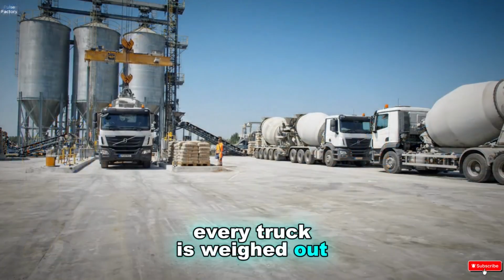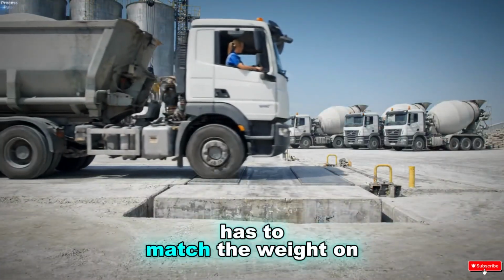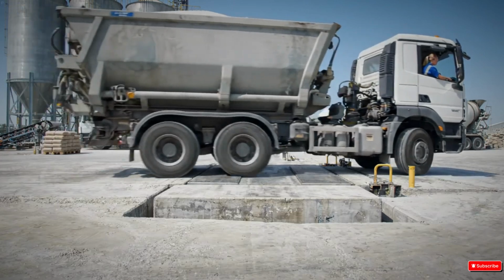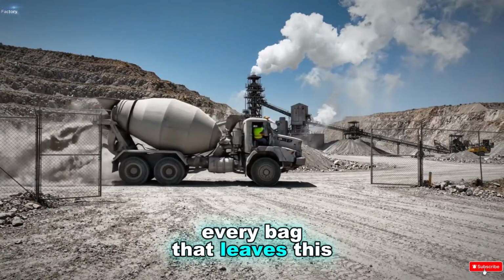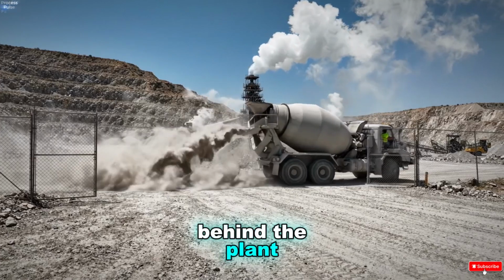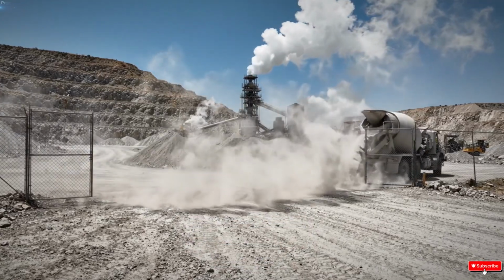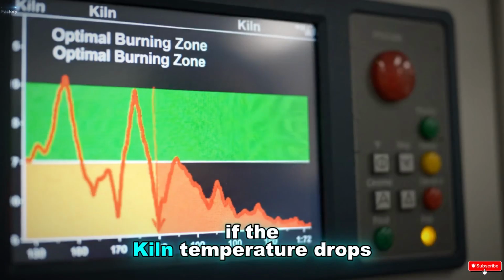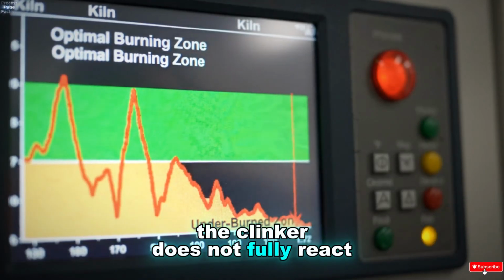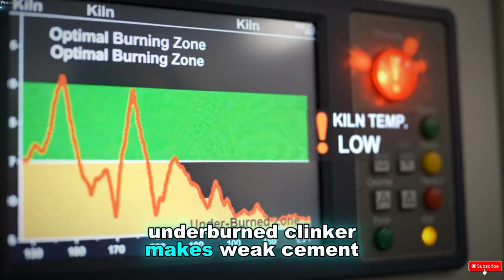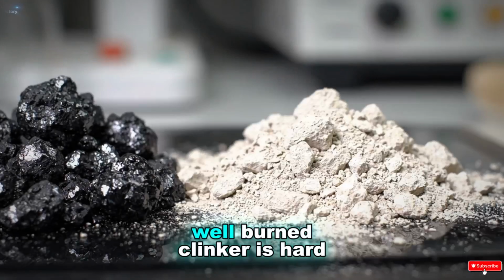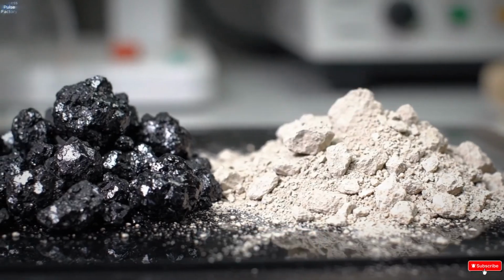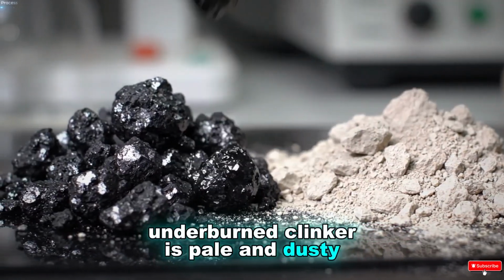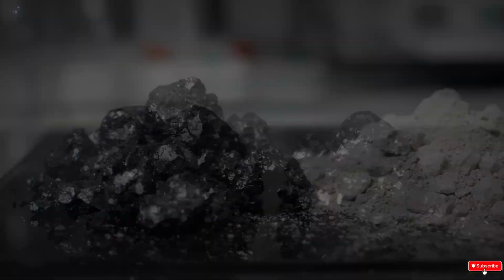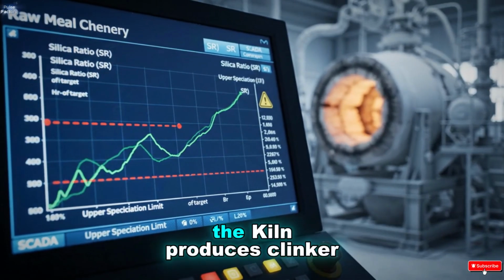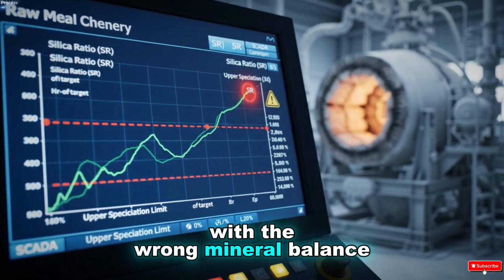Every truck is weighed out, because the weight on the invoice has to match the weight on the bridge. Every bag that leaves this gate started as a mountain behind the plant. If the kiln temperature drops, the clinker does not fully react. Underburned clinker makes weak cement. Well-burned clinker is hard and dark. Underburned clinker is pale and dusty, and it will not make proper cement. If the raw meal chemistry drifts, the kiln produces clinker with the wrong mineral balance.